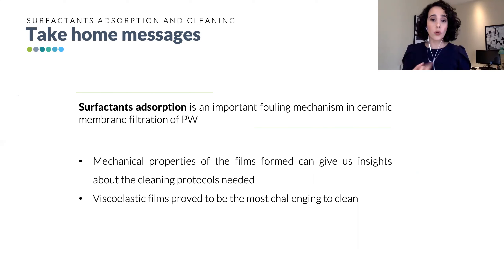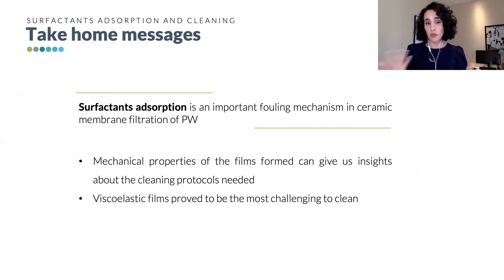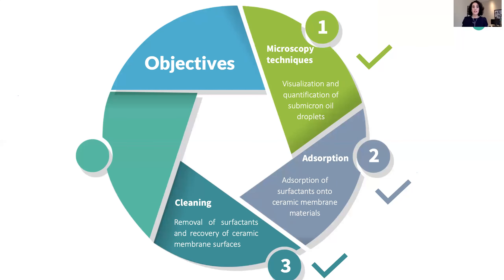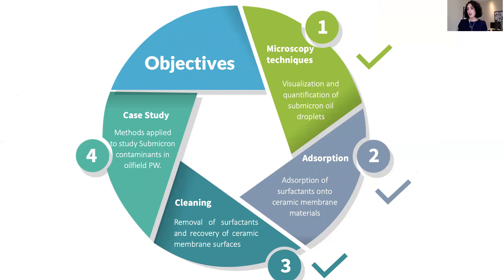Furthermore, the mechanical properties of the films can give insights about the cleaning protocols needed, and viscoelastic surfactant films prove to be the most challenging to clean. This can be further explored to optimize parameters such as cleaning protocols for ceramic membranes, including chemical concentrations, soaking times, and hydraulic flush duration.